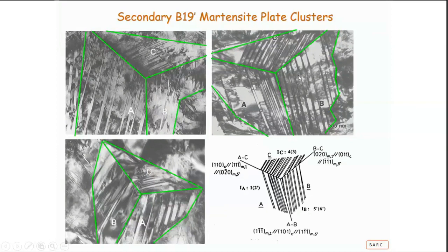The martensite that forms, it forms what is called an invariant plane strain. Now I won't go into that, but it has to fulfill a condition called invariant plane strain, and generally that shear which we talked about earlier is not able to do that. So it is not just the shear. It has to maintain this invariant plane strain, and in order to do that, it needs to have one more shear, and that shear in the case of nickel titanium and other shape memory martensite could be twinning. Slip is also possible, but you don't see it here. So in many of these martensites, you see this kind of internal feature which is called internal twinning, a lattice invariant shear, which in this case is twinning.